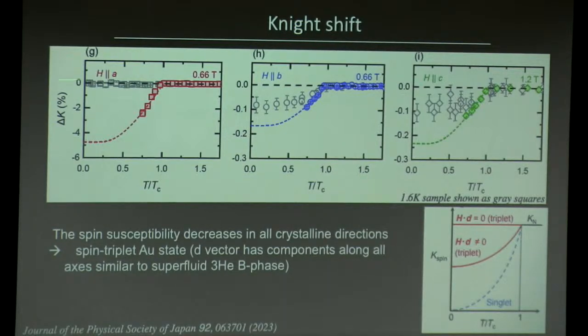In uranium ditelluride we see a very small change—this is not our data, this is from this paper—you see a tiny change in all three directions. The fact that the change is very small tells you it's a triplet superconductor. The fact that you see a small change at all in all three directions tells you that the direction of the D vector doesn't point along any of the principal axes. It's in some other direction.